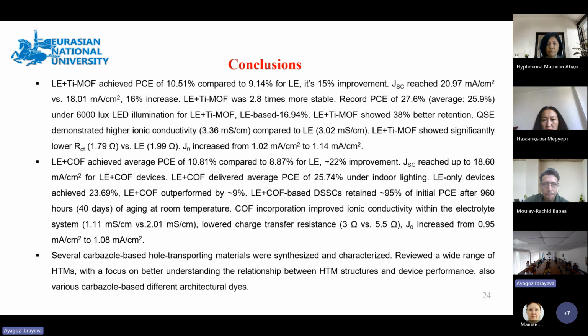In conclusion, I would like to say that when we add Ti-MOF, power conversion efficiency increased from 9.14 to 10.51, which is a 15% improvement. Short-circuit current density also reached 20.97, compared to 18. It is a 16% increase, and the quasi-solid electrolyte was 2.8 times more stable. We also established a record power conversion efficiency for these devices, 27.6% under 6,000 lux.